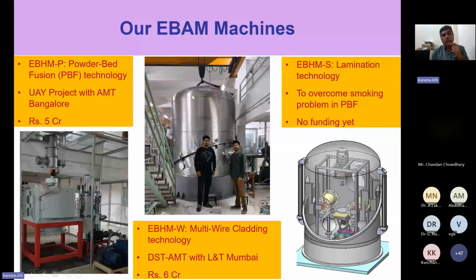We went for a cylindrical dome-like chamber. Size-wise it is much bigger. This is 2.2 meter in diameter, whereas this is only 1 meter in length. But in spite of this kind of diameter, the wall thickness we use is only 8 millimeters, and we don't use any rib except one rib here and another rib inside the chamber. Only two ribs were used for strengthening because the hoop stress takes care of all these issues.